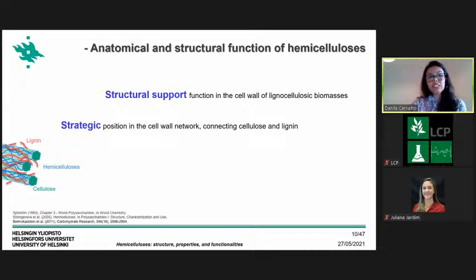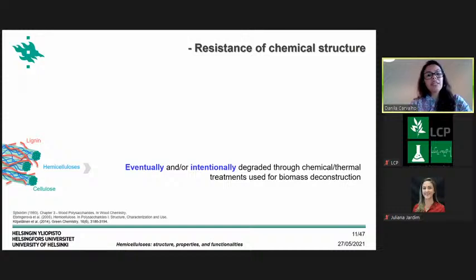Anatomically, the hemicellulose is responsible for the structural support of the cell wall. And if we take a look at this representation here on the side, we can see that the hemicellulose occupies a very strategic position in the cell wall as well, because the hemicellulose occupies an interface between the cellulose and the lignin. And it's for this very reason that the hemicellulose is more susceptible to being attacked during treatments. And then it's the hemicellulose, the main component that is eventually or intentionally degraded when chemical or thermal treatment is applied to the biomass for the biomass deconstruction.